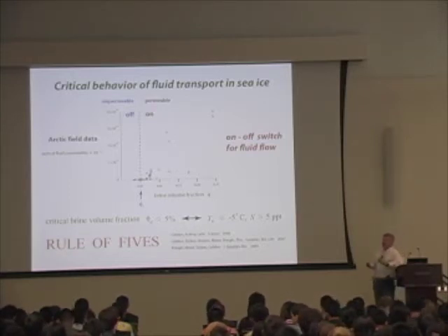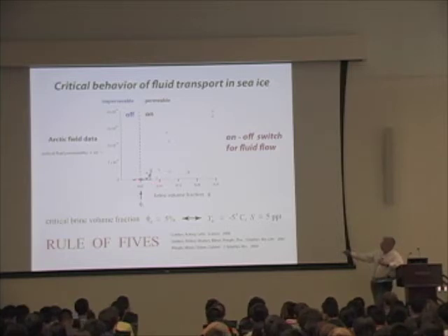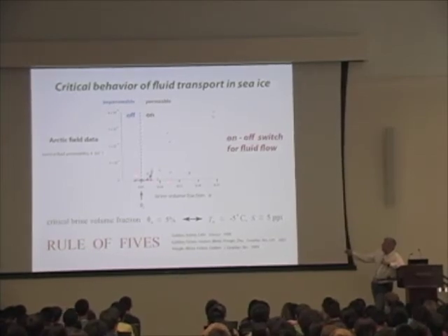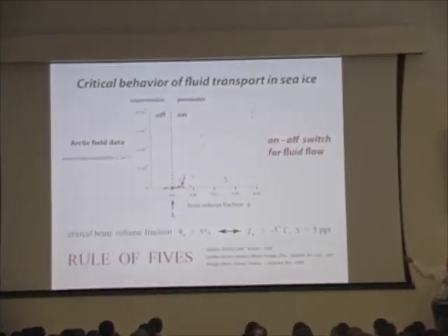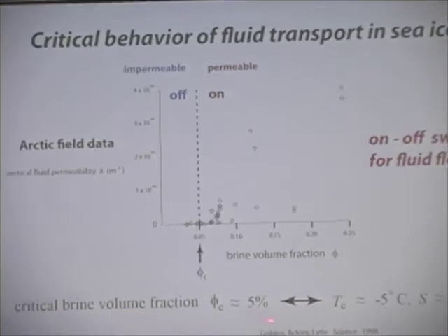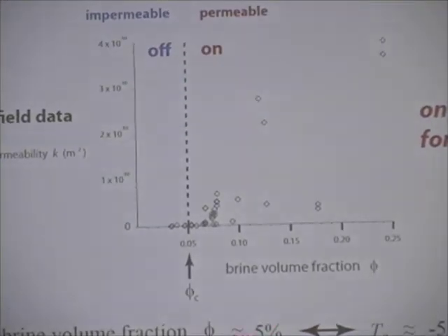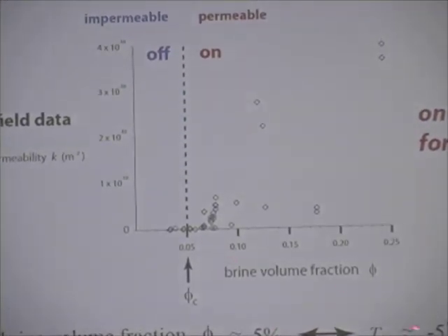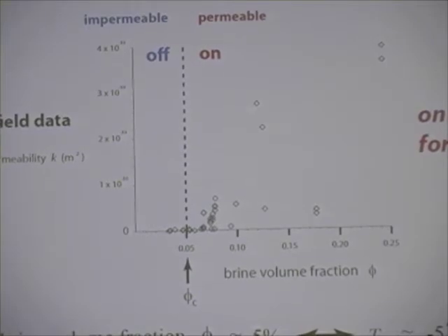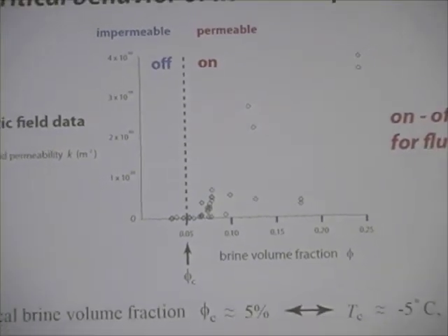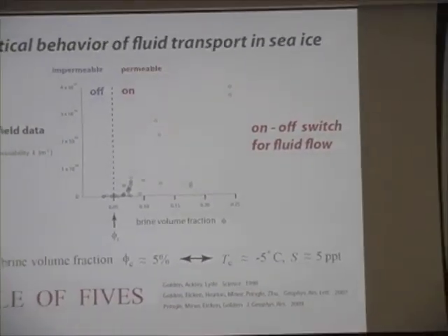Roughly speaking, when the volume fraction of the brine phase, of the fluid phase in sea ice, is below about 5%, the sea ice is effectively impermeable to fluid flow. And for brine volume fractions above 5%, it's increasingly permeable. This critical threshold of about 5% corresponds to a critical temperature of about -5 Celsius for a typical bulk salinity of about 5 parts per thousand. So this is now known as the rule of fives.